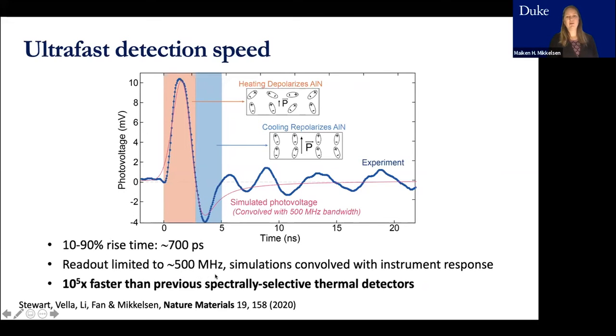So this is limited to around 500 megahertz, which is right where we are. And our simulations that were done in collaboration with Xianghui Fan are shown in red here. These are convolved with the instrument response, which means if the instrument response was faster, we would also have a faster expected response. And this is much faster than any of the typical pyroelectric detectors. But if we compare it with any other spectrally selective thermal detectors, it's about 5 orders of magnitude faster. So we're really getting into a new regime. And that's also what I was alluding to in the title, is how can we use these new nanophotonic structures, where we have critical dimensions at almost atomic scale, to make new ultra-fast devices.